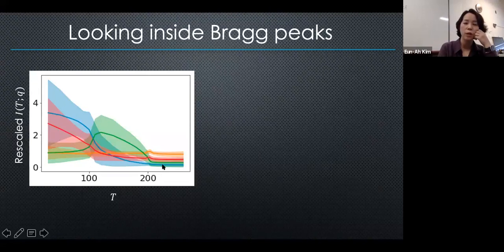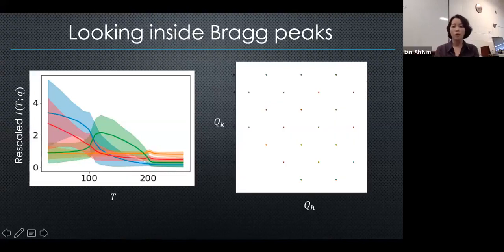Now we are seeing that there are Q points, reciprocal space points, within the Bragg peak, although the Bragg peak is very tight, that are behaving differently. Some are going down and some are going up. And we were really puzzled when we first saw this. My experimentalist colleagues couldn't believe it. This is what it looks like when you plot where these trajectories came from in momentum space. If you look here, these different colors show that within the Bragg peak, there were different behaviors. One was going up and the other was going down, just at that lower transition point.